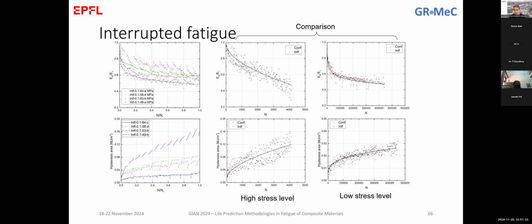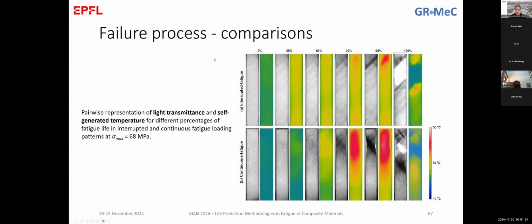The same is observed when we see, for the same stress level, that the stiffness degradation under continuous fatigue, these red dots, is more or less always lower than the stiffness degradation for the interrupted fatigue loading. And the same comparison for the failure surface images, where what we can observe here as an effect of this interruption of load is this recovery that we were discussing before.